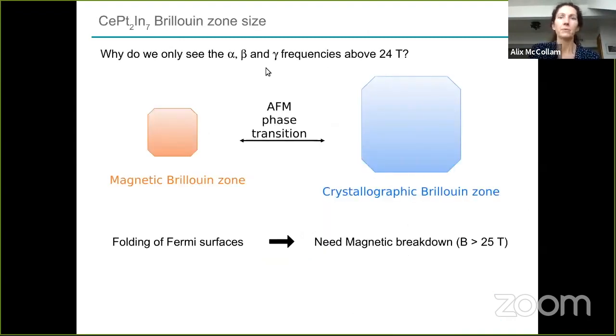Why do we only see the frequencies above 24 Tesla? Is our Fermi surface changing from 45 Tesla down to 24 Tesla, so that we see nothing and then we suddenly have these frequencies appearing? That's not the case. Actually, it's related to magnetic breakdown.